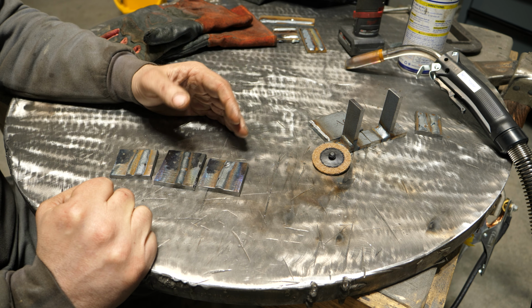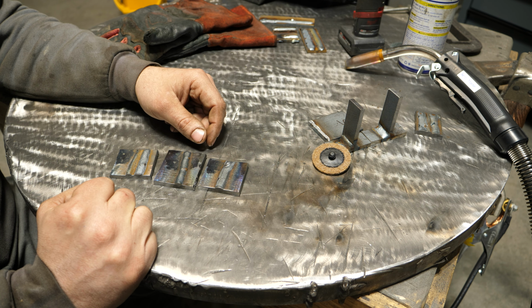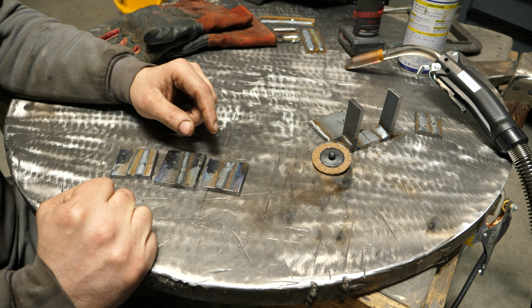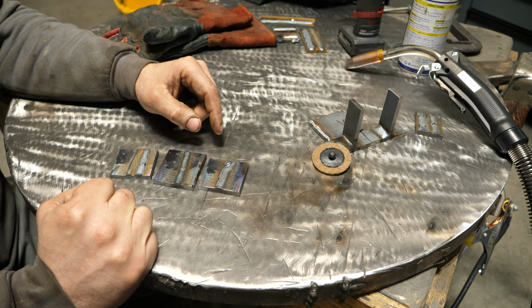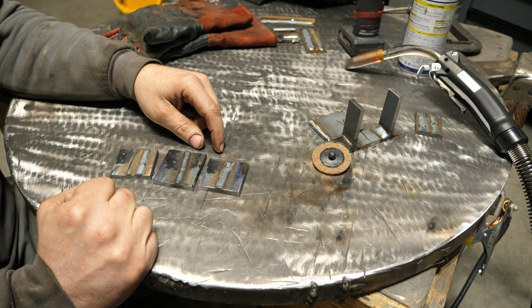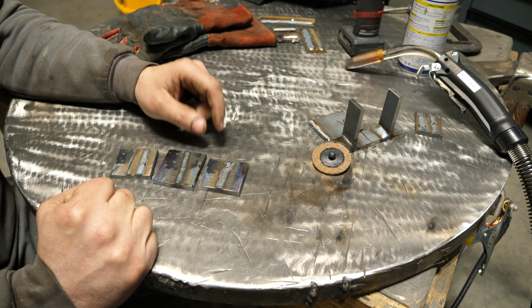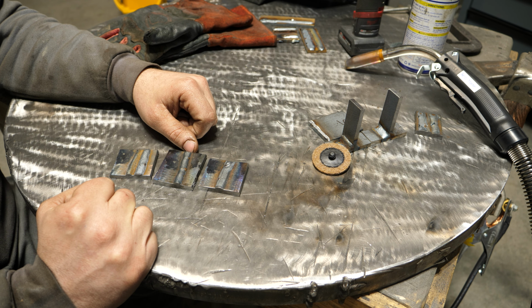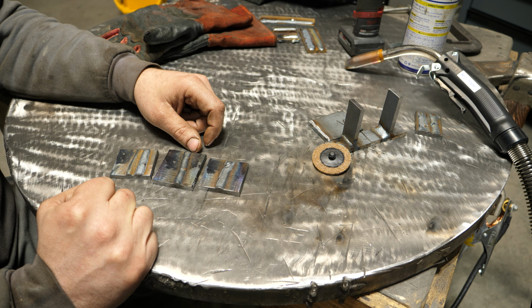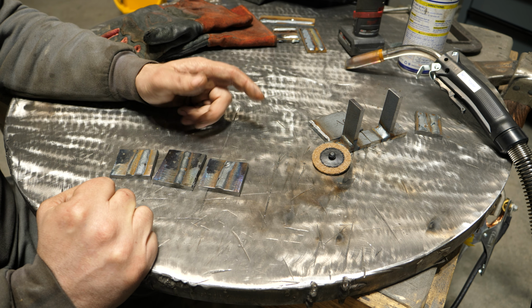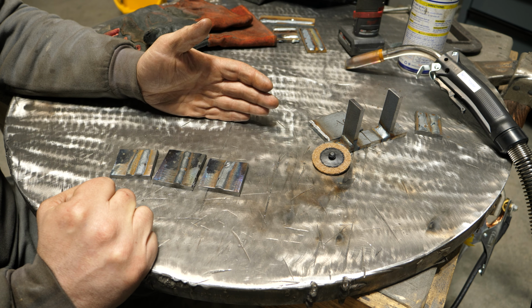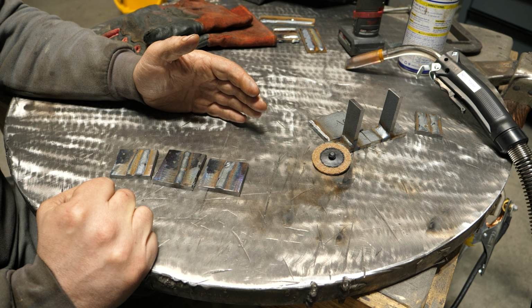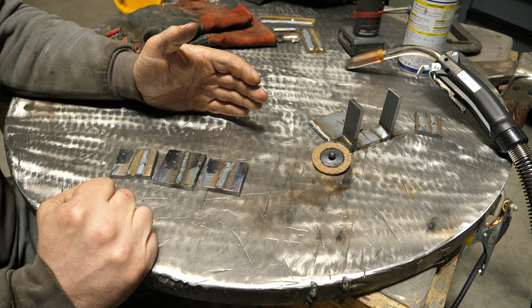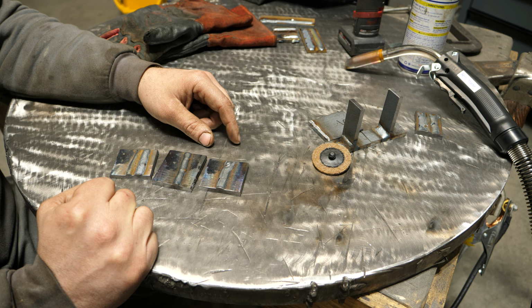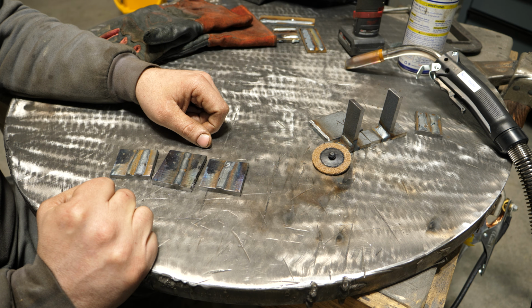If you happen to have a welder capable of spray, it's definitely something you should use if you're welding thicker material. The benefits of that guaranteed penetration are much, much better than the short circuit process, where you can have a highly variable level of penetration, even though welds can look good on the surface. And that's one of the things I didn't mention. When you're spraying and you hear that hiss and not much is going on, as long as your weld looks somewhat decent and consistent, you know that you punched in there.